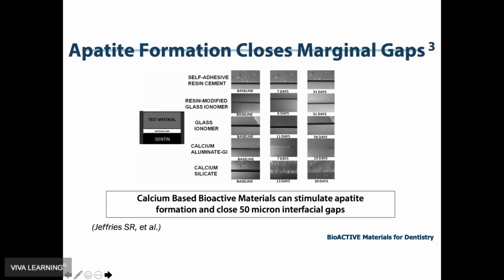This study by Jeffries and his group a few years back shows apatite formation closing marginal gaps in dental cements. What Jeffries and his group did was they took a test restorative material, placed an artificial gap of about 50 microns between a dentin substrate, and placed cement. You can see after so many days in a saline solution, self-adhesive resin cements, there's no difference in the gap. Resin modified ionomers, no difference.